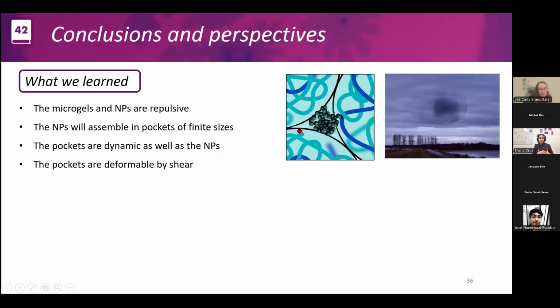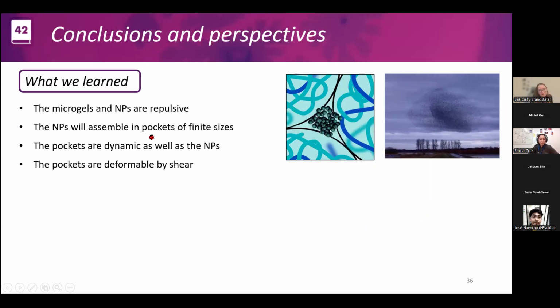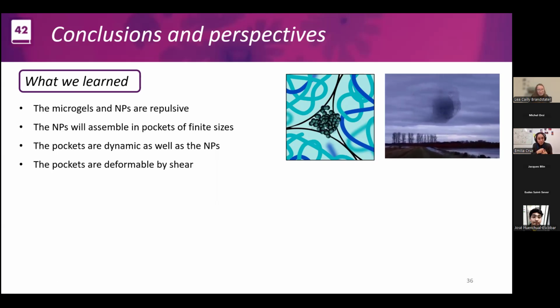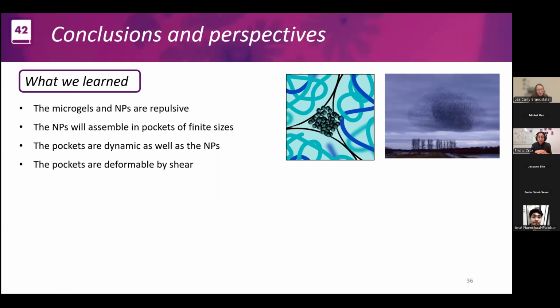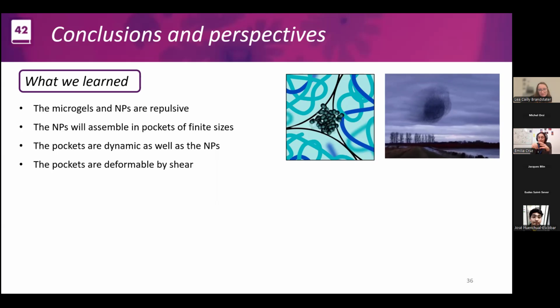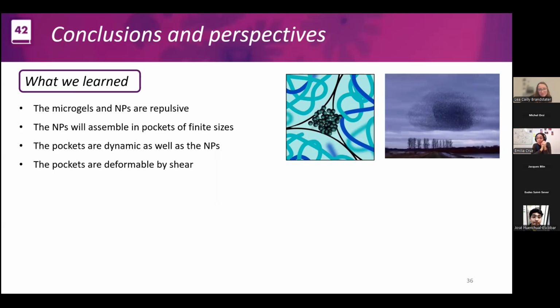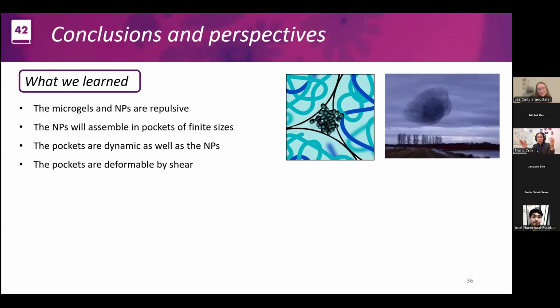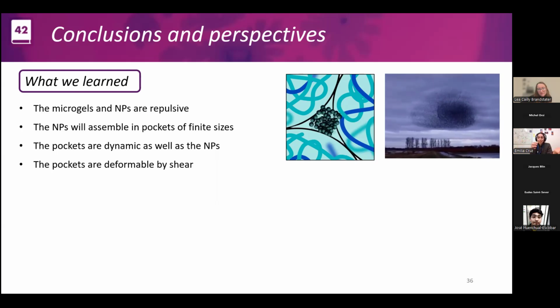So to conclude and talk about a bit of perspectives we have for the upcoming experiments, what we have learned is that the microgels and nanoparticles are repulsive because there are no dramatic shifts in the structure when they come together. The nanoparticles assemble in pockets of finite size within the soft glass, and these pockets are dynamic. So we can probe the dynamics of this soft glass through the nanoparticles with these composites. The pockets are also deformable by shear. So there are many things we have learned that are all in link with this shear-assisted assembly of colloids because we have sheared the system to prepare it. And now by shearing it also during the experiments, we see what's actually happening when the particles are repulsive.